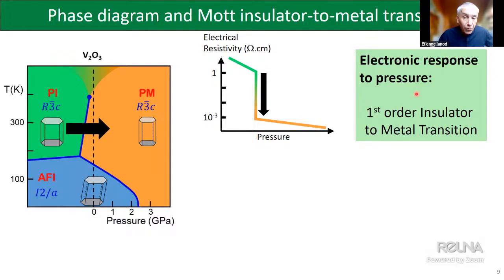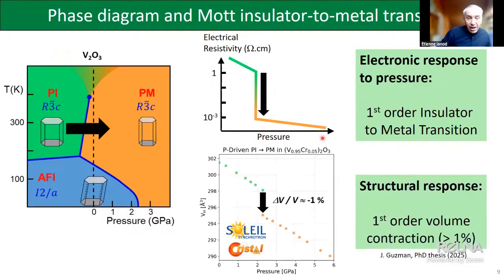And so it's a first order transition. From the electronic point of view, it's clear that we have a big jump. And if I look now from the structural point of view, here you see that the unit cell volume of the material also drops in a first order way, let's say, by 1% close to room temperature. These are experiments obtained by Julio Guzman during his PhD.